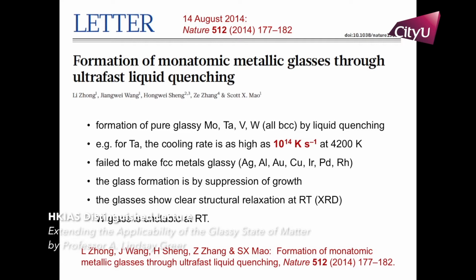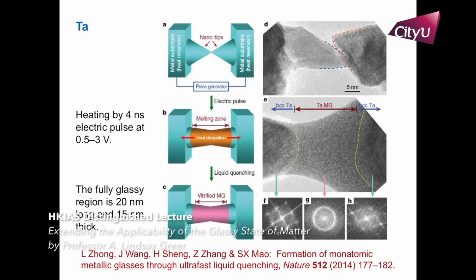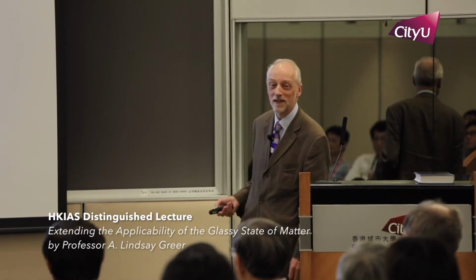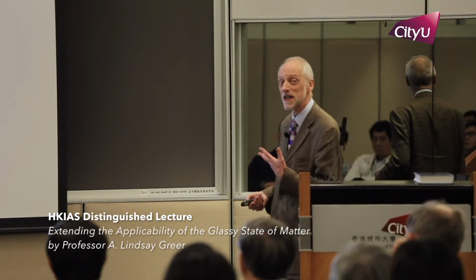This was Scott Mao's work from Pittsburgh. BCC pure metals, quenched at this calculated rather high rate, as you can see, in what is conceptually rather a simple experiment: bring together two nanotips in the electron microscope, put a current pulse through, you melt a little liquid bridge, which cools rather rapidly. What's neat is, if this is, let's say, liquid tantalum, it's in contact with crystalline tantalum on either side. It then freezes into a glass, but you cannot claim that that glass formed because it had difficulty nucleating crystalline tantalum, because it was already in contact with crystalline tantalum. So it could only form if you suppress the growth of the tantalum.